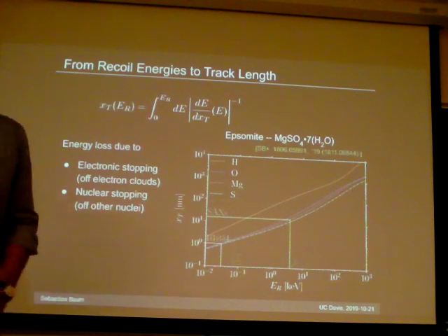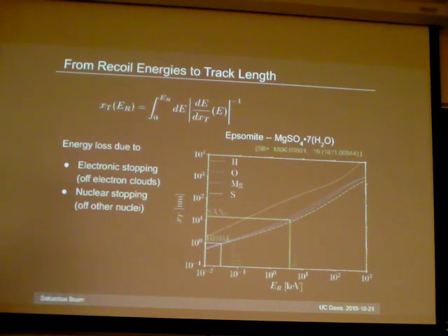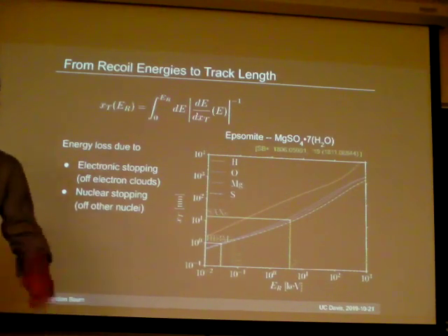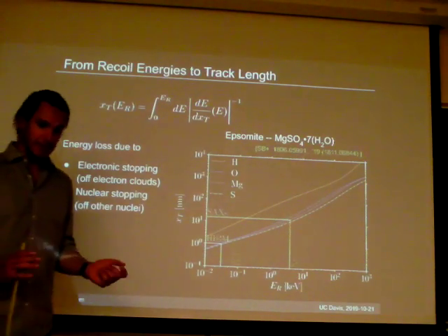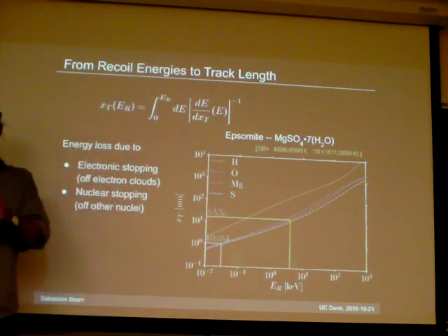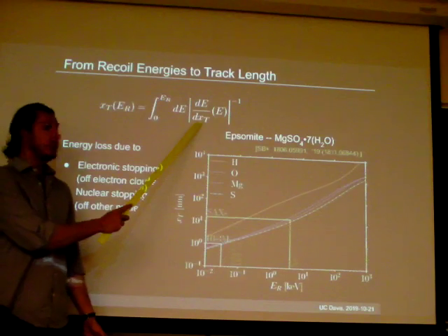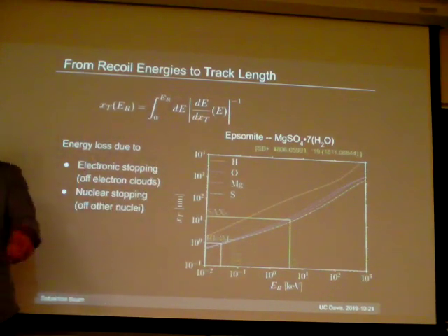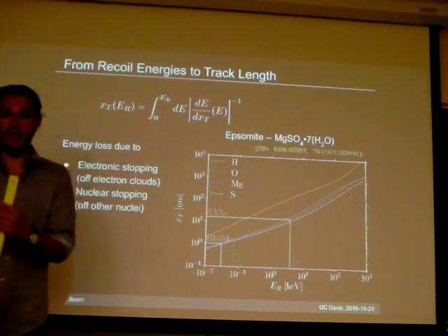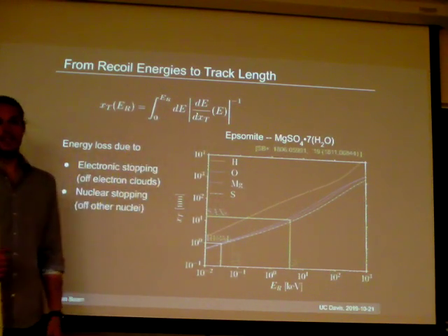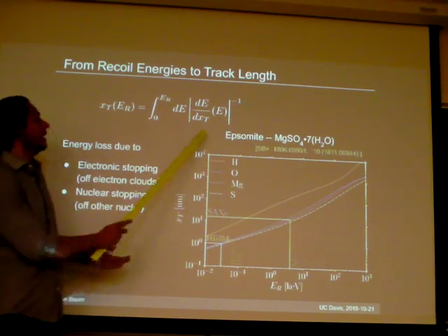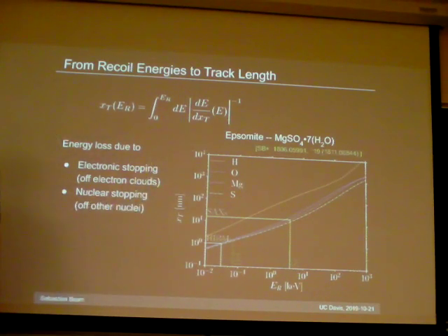All right. Sorry, before we move on, I think you explained it, but why don't you care about the Z line, the H line? So basically, this is a very rough argument. It's not how it actually works. People have understood it since, but the very rough argument, and qualitatively it holds, is there is a threshold to the stopping power you need in order to deposit enough energy locally to create a lasting track. And the lower your charge is, or it's the charge to mass ratio that matters in the end, but the lower your charge is, the lower your energy deposition is going to be. So this is why hydrogen doesn't give you a lasting track normally. You just don't deposit enough energy.